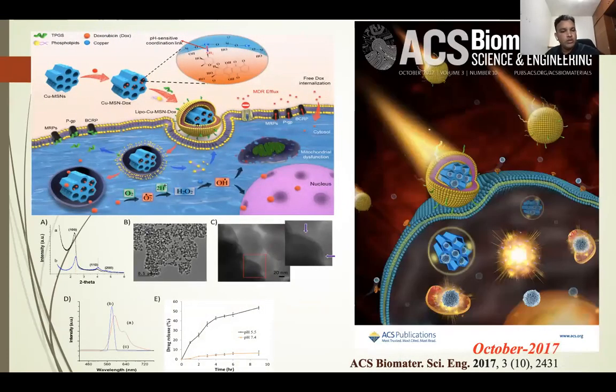And in another work, we generated the same copper MSN, and we loaded the DOX through the same coordination interactions, like Cu and DOX coordination. And after that, we coated liposomes for efficiently targeting and entry into the cancer cell, overcoming MDR, multi-drug resistance. The MDR itself is like, if you have normal drug encapsulation or normal drug delivery, these pumps, even after entry, will try to kick out the drug molecules. So we put the drug molecules inside the silica and coated the liposome as well as TPGS. This TPGS will try to stop the MDR pump in the cell so that the drugs can be delivered feasibly inside the endosome. And this copper chemistry as well as DOX chemistry works together to create OH radicals.